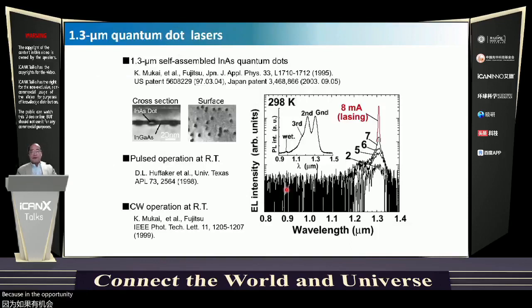Regarding the 1.3 micron quantum dot lasers, Fujitsu Laboratory, as I mentioned before, developed 1.3 micron self-assembled quantum dot structures. And the University of Texas realized pulsed operation at room temperature. Finally, CW operation was realized by Fujitsu Laboratory. And you can see the lasing spectrum from the quantum dot laser chips. Below the threshold, you can find the luminescence corresponding to the ground state, the first excited state, and the second excited state. This evidences that discrete energy levels are realized inside the quantum dot lasers.